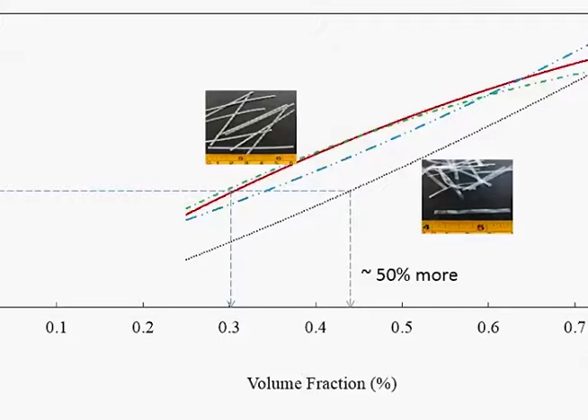With 10 different synthetic fibers, we had varieties of fibers. Some are straight, some are crimped, embossed, twisted, low stiffness, high stiffness. Among those, you see here, if we use embossed or somewhat stiffer fibers, we get more residual strength ratio with less quantity of the fiber versus this one. If we use straight synthetic fibers, we have to add more in order to get 20% residual strength ratio.